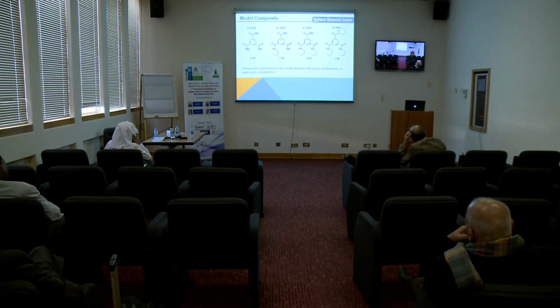Of course, since we used water or methanol as solvents, these two solvents have OH groups, and we are relying in our work on the residual carboxylic groups on the polyamide layer. So there will be a competitive reaction between these hydroxyl groups of the solvents and the amine groups of the polyamidoamine. So we made a model compound, and here we can see the component ratios found in the model reactions with equal stoichiometry of water and N-butylamine, and we found that most of the subunits obtained are from the reaction of the amine with the carboxyl groups.